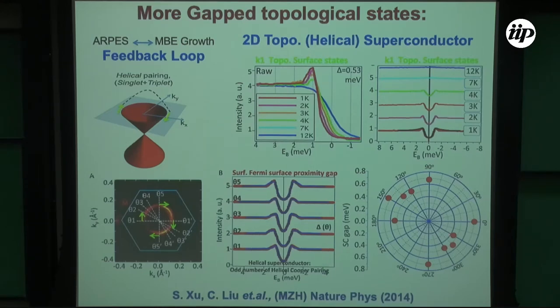Well, we can try to analyze it further and see whether it fits some BCS function. We haven't done that in great detail, but we could. I'll show some fitting of the gap in a moment. We can also do that in a momentum-resolved way, so we should be able to tell if the gap is isotropic or anisotropic. It's something you can't immediately do with transport. We can tell you exactly how anisotropic the gap is. Within the resolution of the experiment, we see it's fully gapped. There's no node, so it's not like high TC d-wave where there is a node.